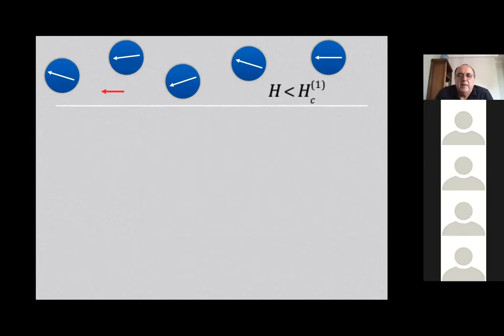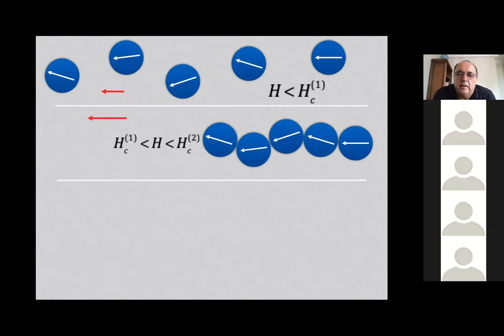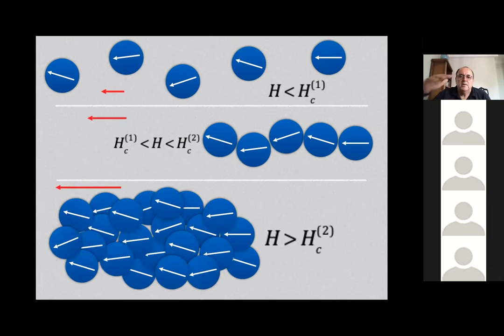Well, if we apply a magnetic field of small strength in a ferrofluid, here we have a sketch of particles, whose magnetic moments, when we put a magnetic field, have a main orientation of the magnetic dipoles parallel to the magnetic field. But if we increase the field to a first critical field HC1, what we have is not only the orientation of the magnetic moments, but also the formation of linear clusters, some aggregates which resemble lines here, until we reach a second critical point, HC2, where we have the formation of bundles. So these lines will attach to each other and form very big aggregates. Most of them can be observed even in optical microscopes, so micron size can be formed.